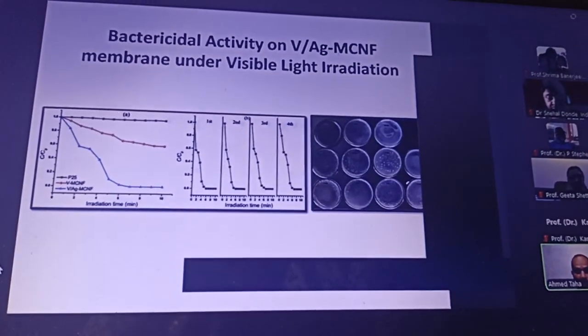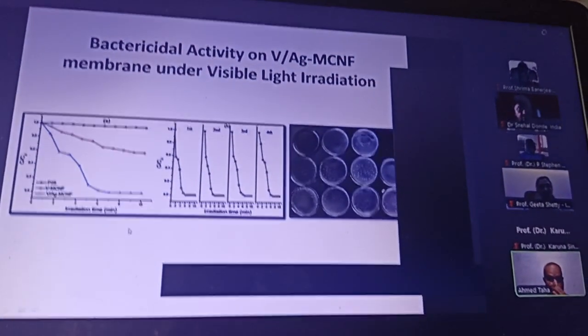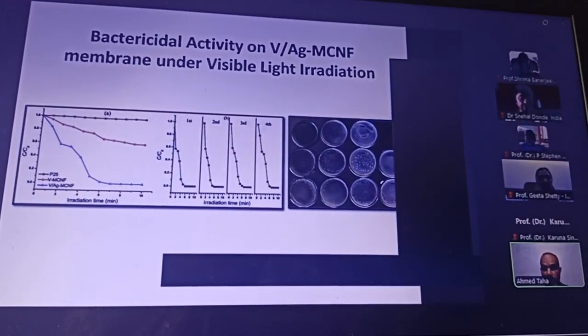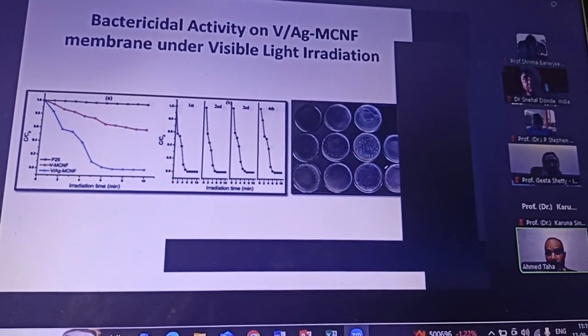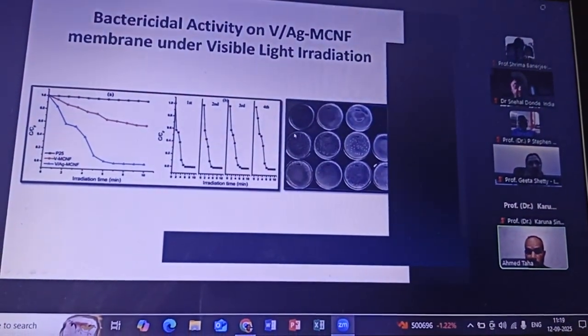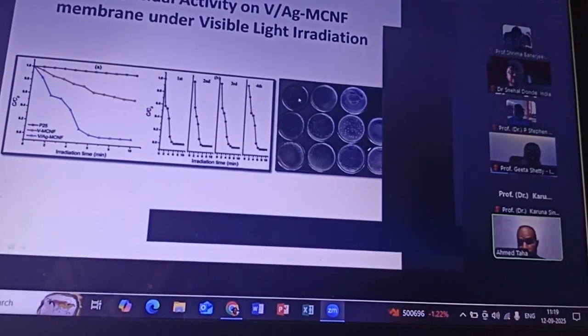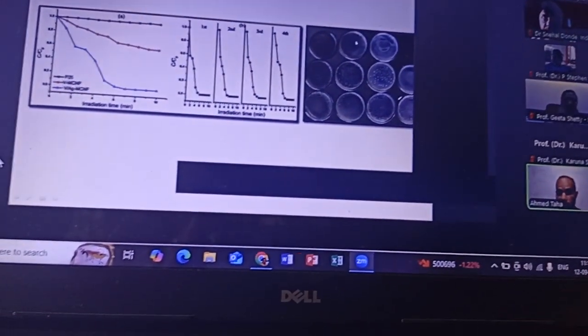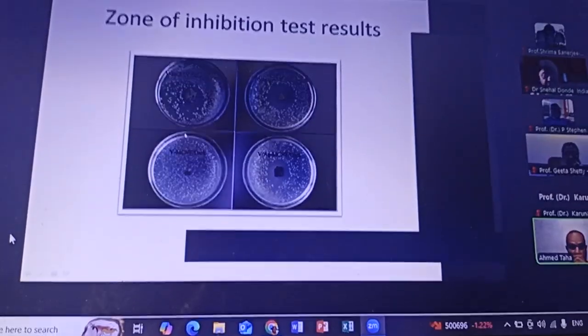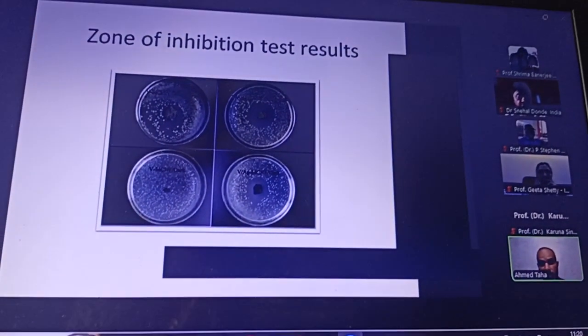Here is how we took our material and mixed it with the water that has the bacteria, and then we plated it on the plate, as you see, and exposed it to the light. And you can see after some minutes there is no growth of the bacteria in the petri dishes. And here we did also to confirm this result the zone inhibition test.